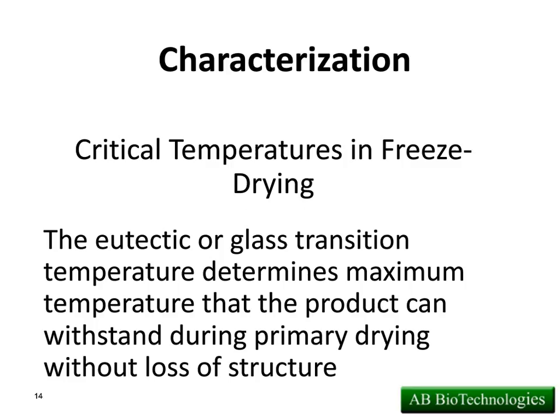Okay, so the critical temperatures in freeze drying, the glass transition temperature and the eutectic melting temperature, for the most part represent the warmest temperature we can go during primary drying without collapsing the product. So this is something that we have to pay very close attention to, to make sure that we're drying efficiently. We're not going to be 20, 30 degrees C below this temperature because we know it's going to really slow down that process. But we don't want to be right there at that critical temperature, because then we run the risk of collapsing or eutectic melting the product.